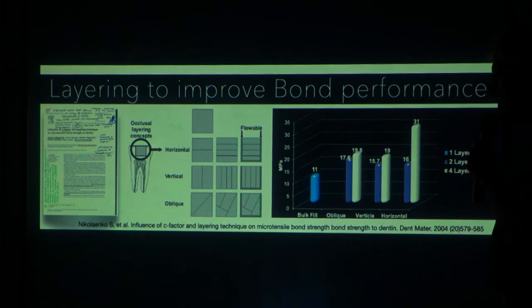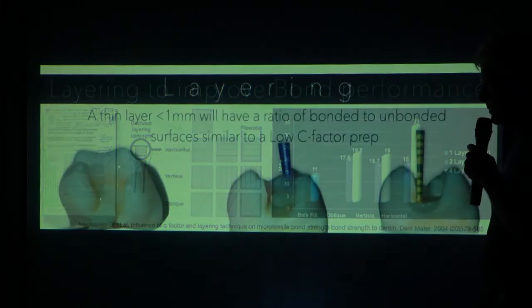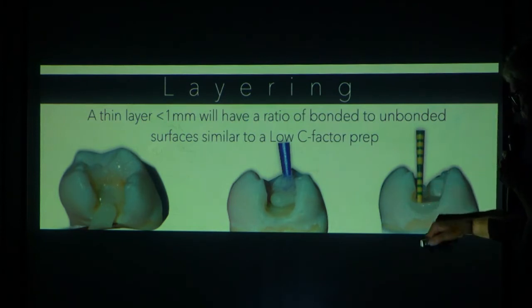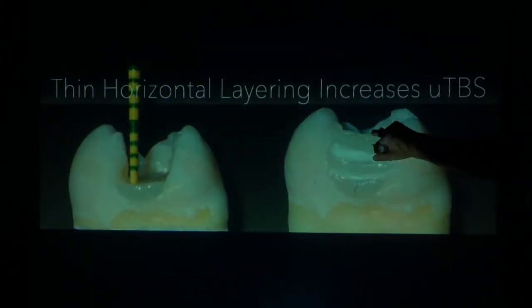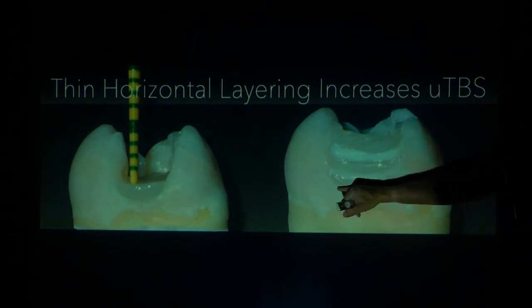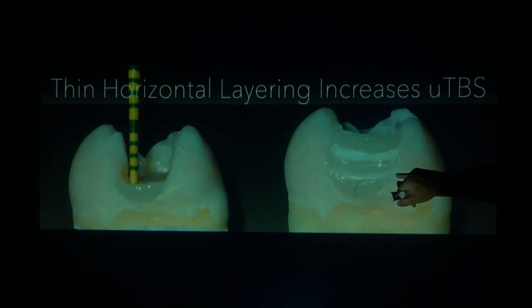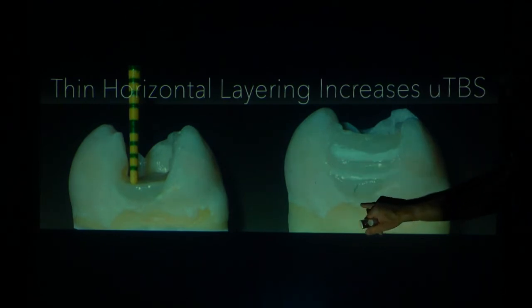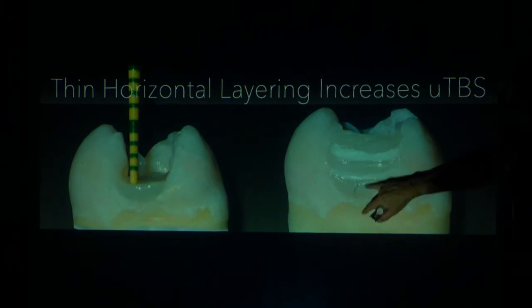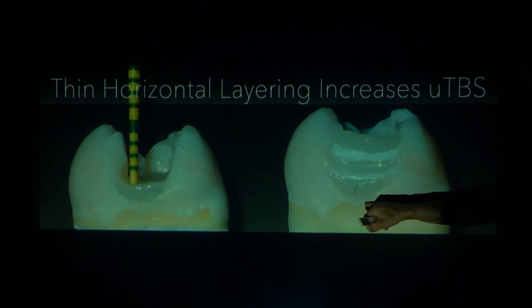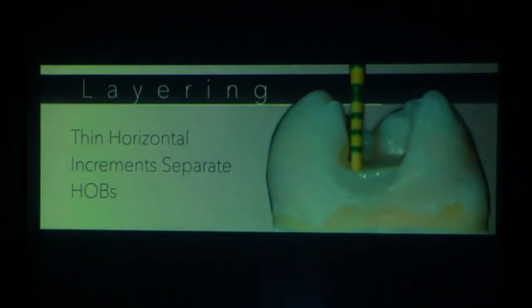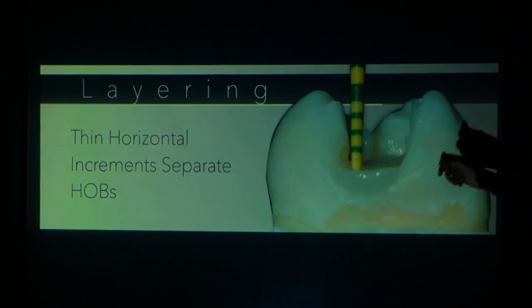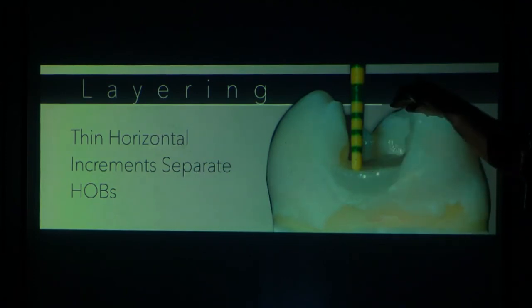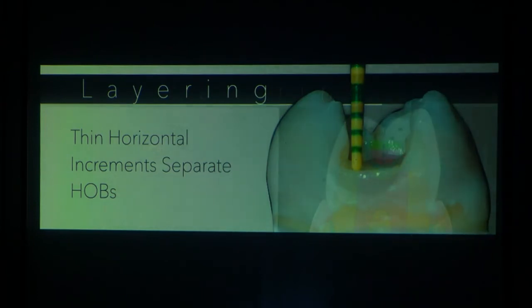And that's what a stress-reduced direct technique engages. And so these thin layers, as Davey said, we're stacking plates on top of plates on top of plates. And that means that this area here has more time to develop its bond strength before there's another layer here. And this layer here does not affect this layer. But this 2 millimeters, if it's immediately put on top of the immediate dentin sealing, then you lose your bond strength 50%. So thin horizontal increments separate the hierarchies of bondability, low bondability from high bondability, for a certain number of minutes.